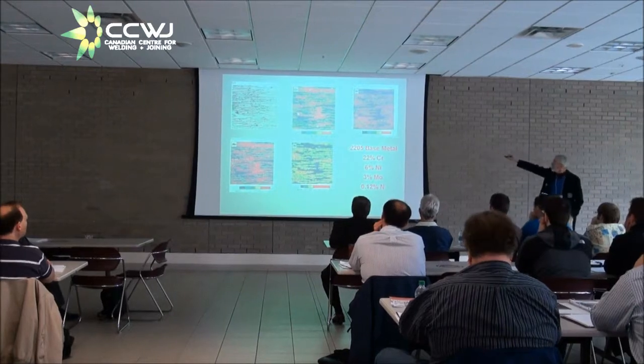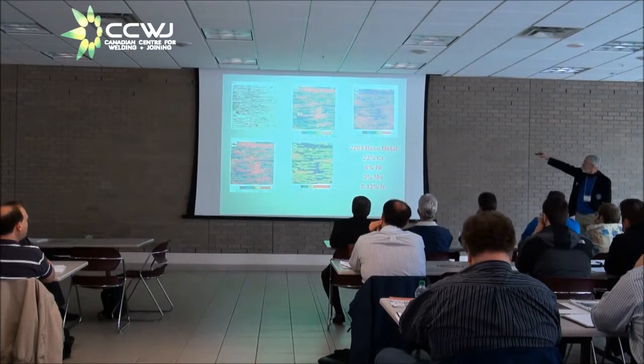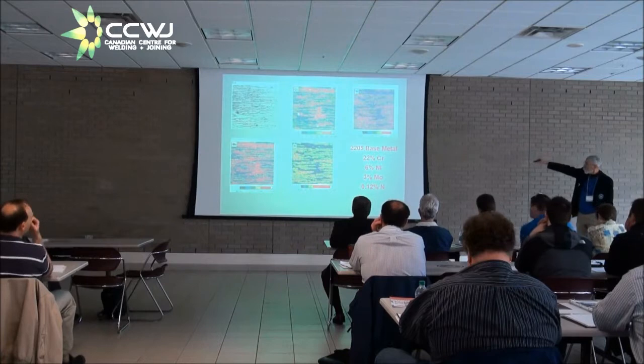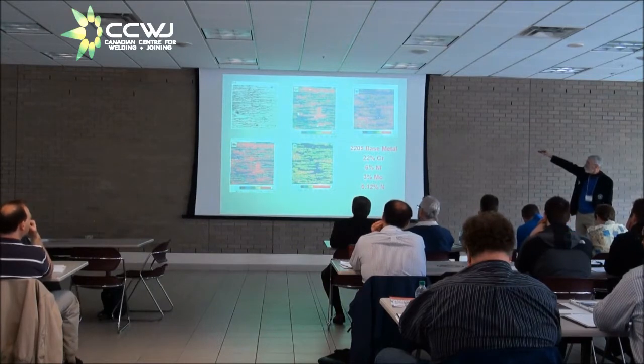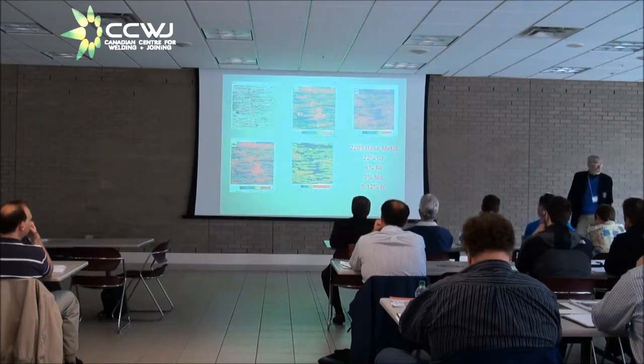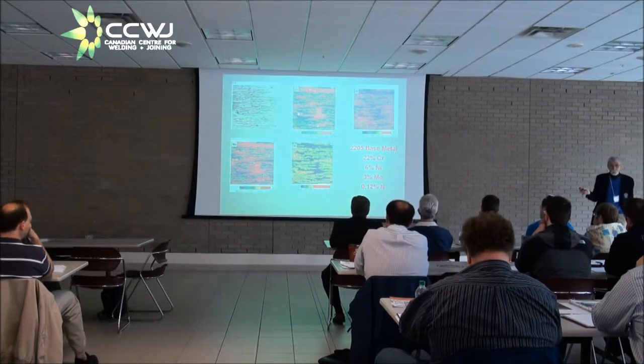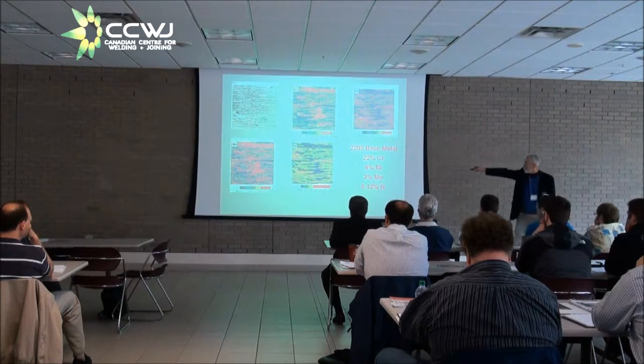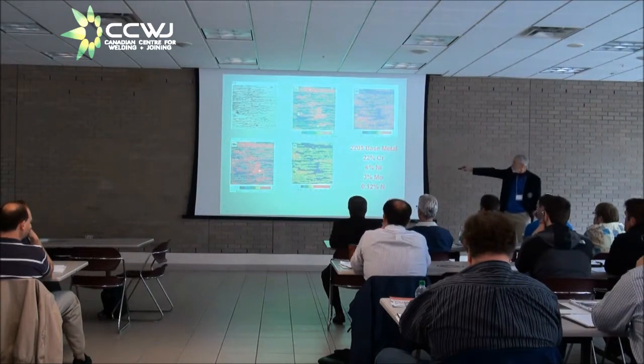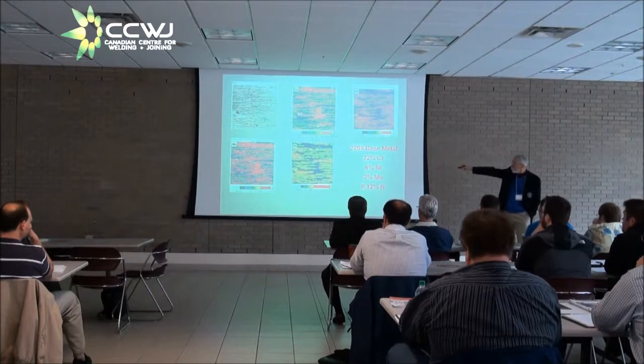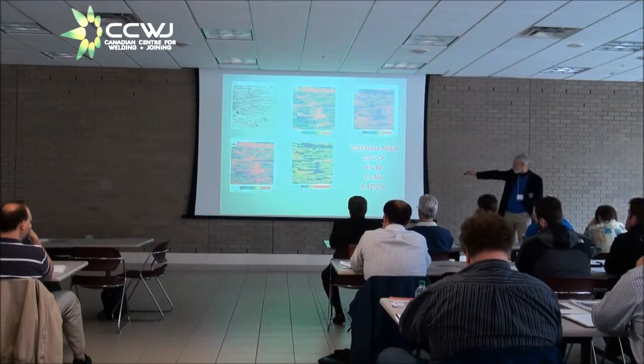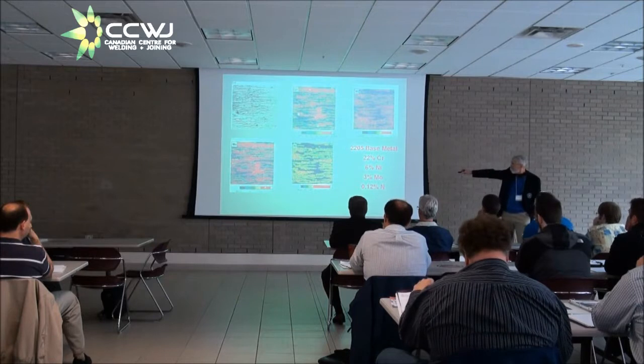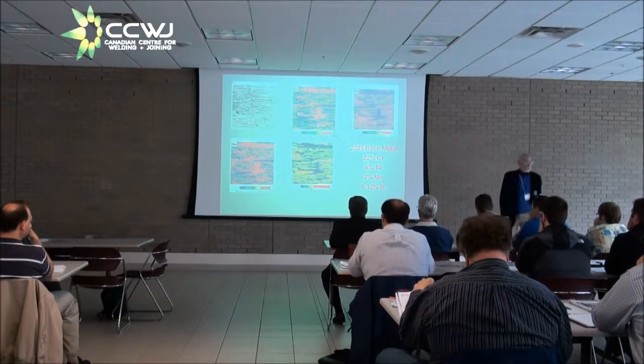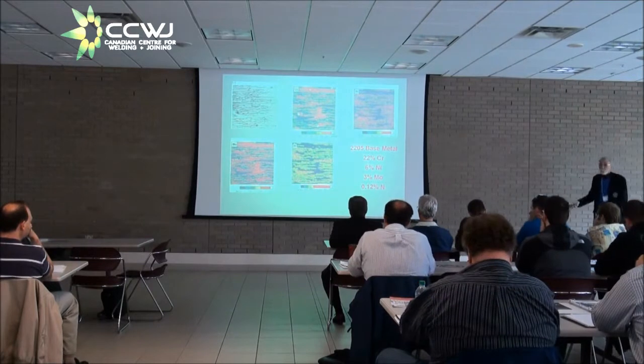Conversely, if you look at the nickel map, what you see over here in the ferrite area is low nickel. And now the blue color corresponds to 5% nickel. Okay. The alloy is nominally 6% nickel, so you got 5% nickel in the ferrite. And over in the austenite area, you have the red color, which corresponds to about 7 or 7.5% nickel. So the nickel has also partitioned. The molybdenum map looks just like the chromium map. The rich molybdenum area is the ferrite, the low molybdenum area is the austenite. And now the alloy is 3% molybdenum, but the ferrite contains almost 4% molybdenum, and the austenite contains 2.5%. So there's a partitioning of molybdenum.